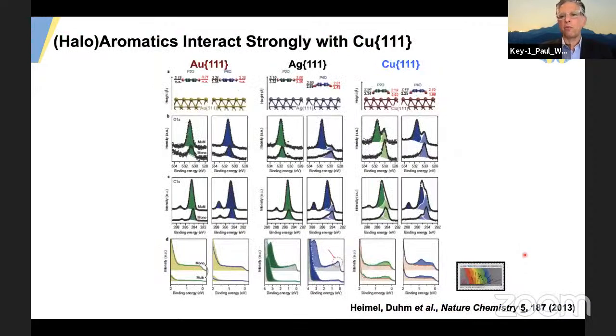Okay, and the reason we use copper surface in this case is that it interacts strongly with aromatics. So if you look at the gold 111 surface, the close-packed surface, aromatics sit far off the surface. We've actually measured the interactions of benzene on gold 111 and shown that under the right tunneling conditions, we can peer right through the benzene and show that the reconstruction of the gold 111 is not lifted with the aromatics on it. On a silver surface, aromatics sit a little closer, but the copper strongly interacts with these reactants, intermediates, and products.